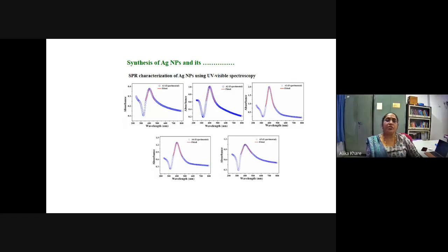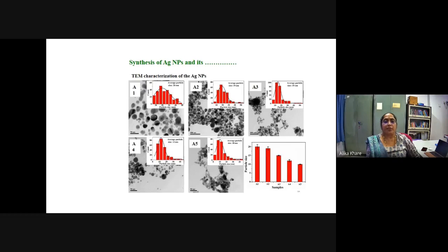This shows the surface plasmon characterization of the nanoparticles, and one can see there is some variation in the surface plasmon property. In some cases it is very narrow, in some cases it is very broad. This is the particle size distribution, and one can see from this summary histogram that the particle size is changing under the various controls.